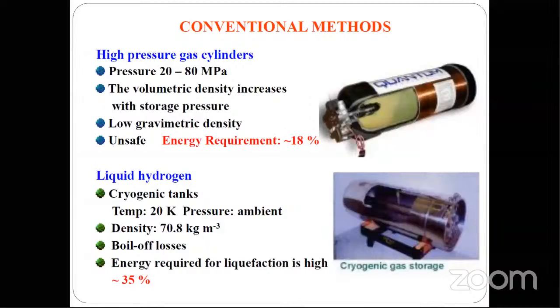And one more main drawback of liquid hydrogen is that for liquefying hydrogen, you have to spend around 35% of the energy content in the hydrogen. If you calculate how much mechanical energy you have to give to reach 20 Kelvin, that is around 35% of the energy stored in the hydrogen. So it means that you can have only 65% of the energy.